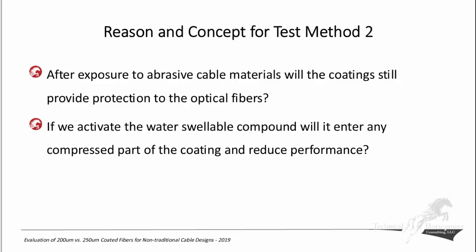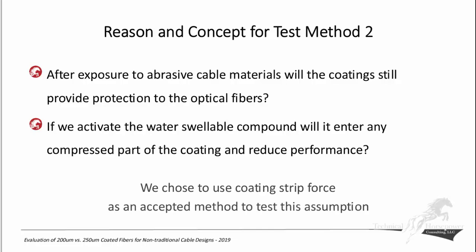So we looked around and we said, there's actually a pretty good test that's out there right now. And to that end, we chose to use coating strip force, because it's pretty much been an accepted method to test the quality of your coatings. If you looked at coating strip force before we, if you will, beat up the fiber, and afterwards, you have a pretty good idea of whether or not the moisture and the mechanical damage did anything to the coating. So we use that as our preferred qualification for test method 2.